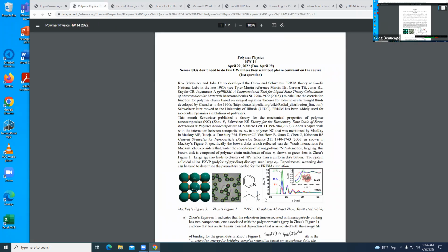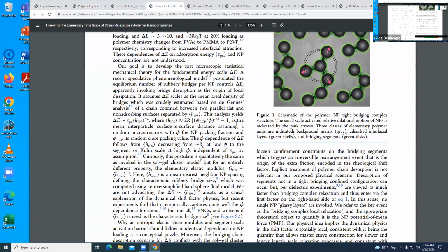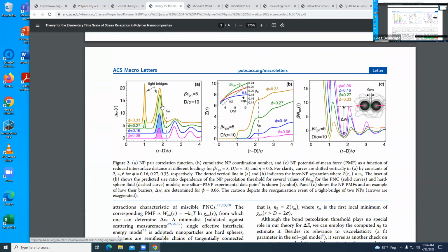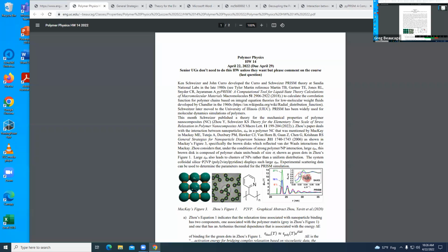One thing becomes obvious later on if you look at the Yethiraj paper. So this is his correlation function, and this is increasing concentration, right? 6, 16, 27 in Yethiraj, and his is something similar to that. I don't know what it is. So the position of the peak doesn't move. That's kind of a problem, because when you measure the X-ray scattering, the peak moves. The peak is the position of the particles relative to each other. So as you increase concentration, they move closer together because there's more of them.